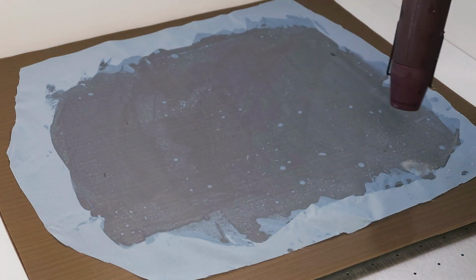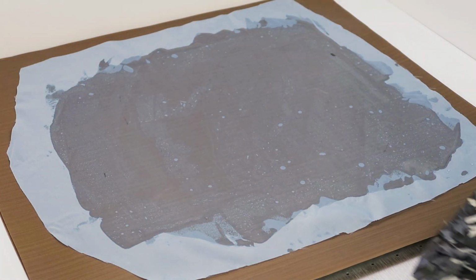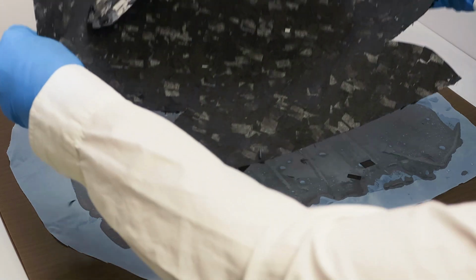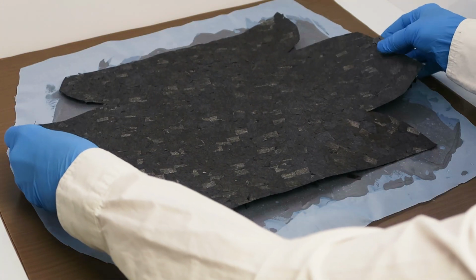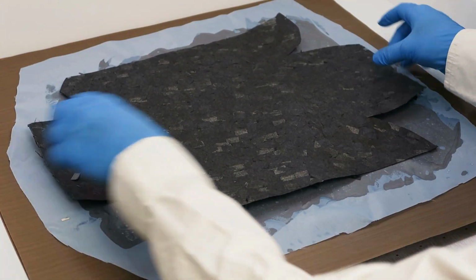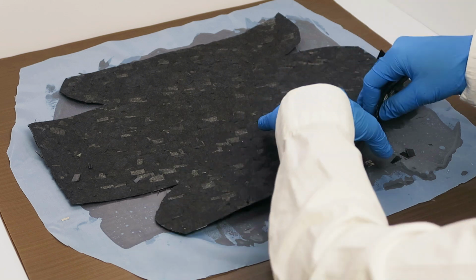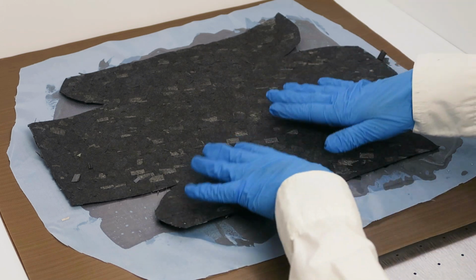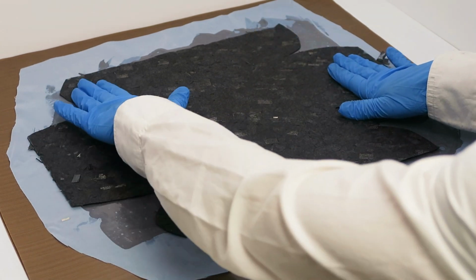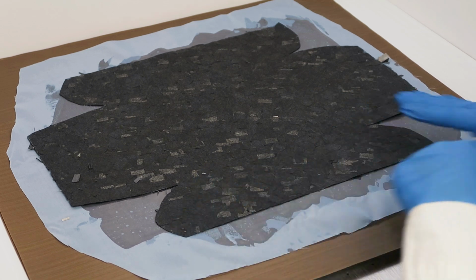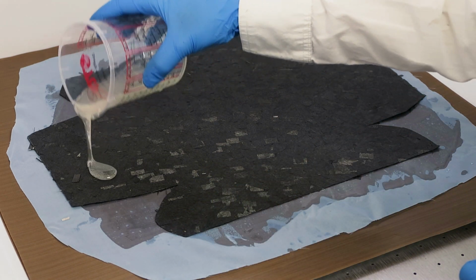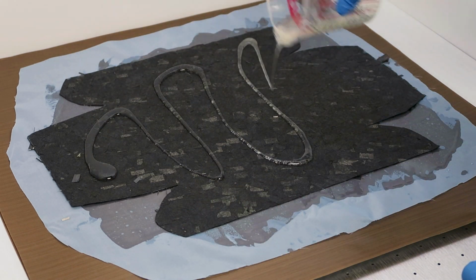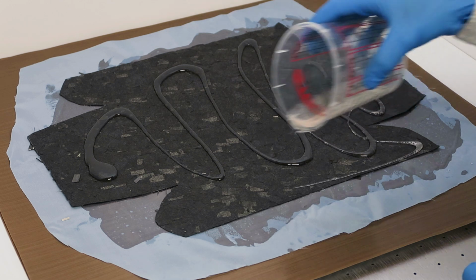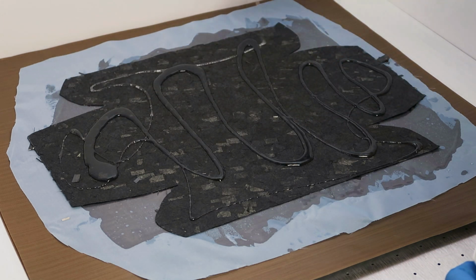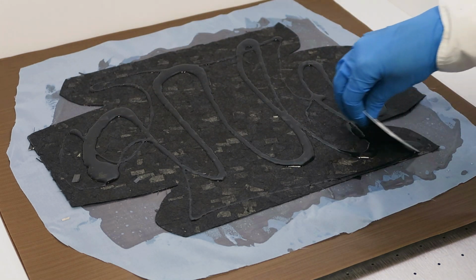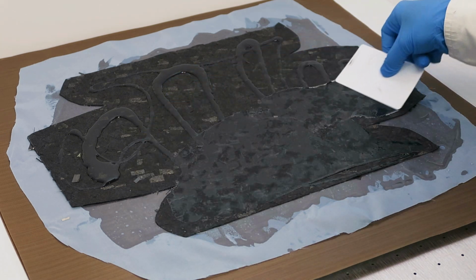I spread epoxy onto the peel ply first, trying to reduce the amount of air bubbles I introduce by using a plastic card as a scraper to spread the resin instead of a brush, and a heat gun to pop remaining bubbles. I then flipped the carbon fiber fabric right side down onto the peel ply so I could saturate it with resin from the back, which is the carbon veil side. If you try to add resin to the front of this type of fabric, the pieces of carbon get all messed up and come unstuck because spray adhesive and sizing both dissolve in epoxy.